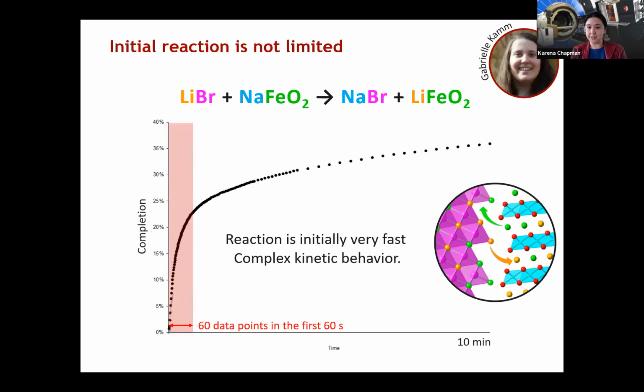So we can look at these reaction kinetics. Now we're looking at a single temperature. Even though we expect solid state reactions to be slow, we were surprised to see that actually we're getting a lot of reaction happening - most of the reaction was happening in the first 60 seconds. So very fast initial kinetic behavior, and some complex kinetics behind here where it's definitely nonlinear.